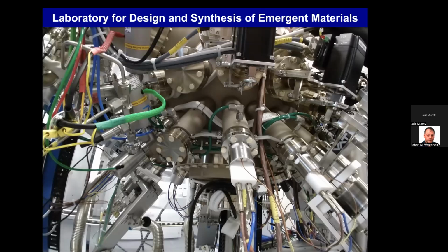What is the error rate for materials made with MBE? And what are some of the detection methods for that? So state of the art is about 1% control. You can do better than that when you have specialized growth techniques like monolayer adsorption control. But when you're really just at the hit and stick, about 1%.